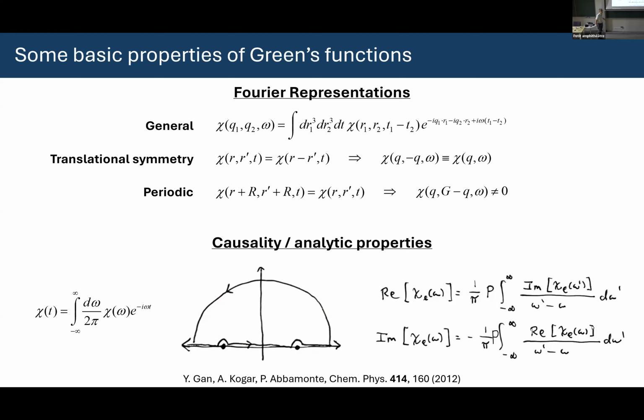Can I make a comment about that? Yeah. It's not always, so also sometimes it's implicit. For instance, we want to know the superfluid density in a superconductor, which is defined as the integral of the delta function. Yeah. We can't measure that. So we measure low frequency. Yeah. We measure a 1 over omega dependence of the imaginary part. Right. And the coefficient comes from the integral. Yeah. So you measured one frequency there and your error is 0. Yeah. Right. So that's the case. So there are many ad hoc cases where you sort of have to know what you're doing. Right.